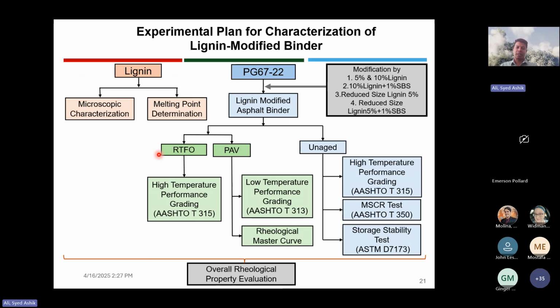Then we conducted short-term and long-term aging through the short-term and long-term aging protocol. We got the RTFO and PAV samples. We have done the DSR testing again on the RTFO sample to find out the high temperature performance grade.